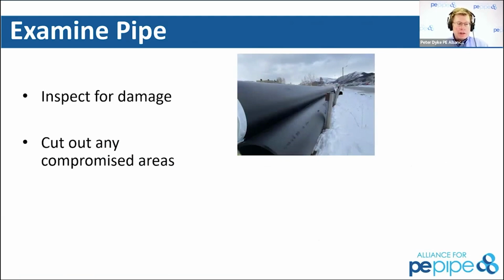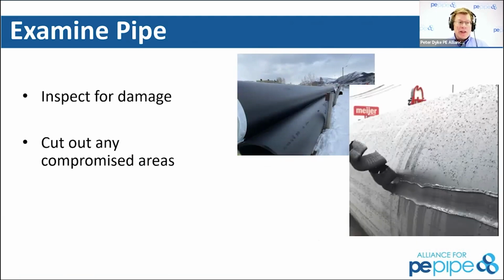Okay, good. Inspect it. Cut out any compromised areas. The cool thing is with that jagged edge there, you can cut that out. If it's greater than 10% of the pipe wall, you cut it out, face, fuse.